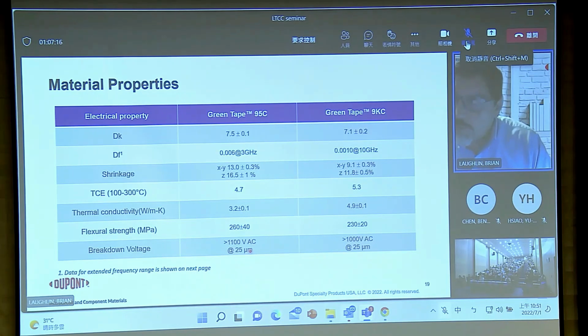They both go through shrinkage. They're chemically different systems. The shrinkage is slightly different, and therefore the pastes that go with them have to be their own specific family of paste. But they're repeatable with about 0.3% shrinkage from sheet to sheet, box to box, lot to lot. And so you can rely on those kind of numbers. And I mentioned before that 95C, you can change it by a couple tenths just by lamination pressure.